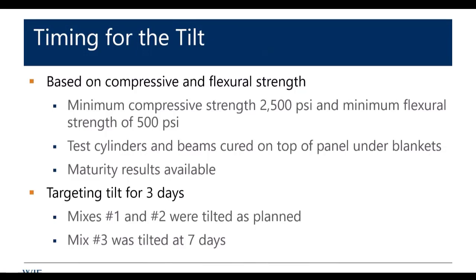Timing for tilt, as I mentioned, the criteria is 2,500 PSI compressive and 500 PSI flex. And the test cylinders and beams were placed on the slab with the blanket over them. And how many of you have done this and that's how they do the cylinders? Come on, be honest. You guys ever see that? They just put them on top, right? Normal.